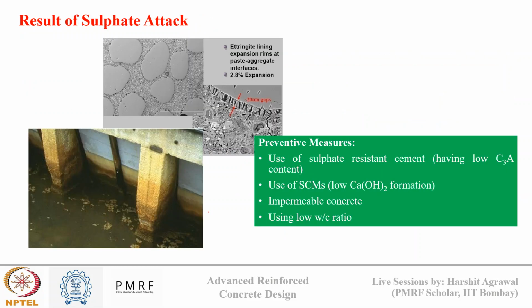Now we can see this effect of sulfate in the image. In the first image you can see the cement paste interface where ettringite lining is present, and it has led to 2.8% expansion. In the second image you can see how a submerged column is experiencing bulging here and here due to sulfate attack.